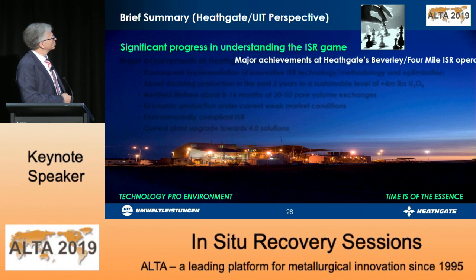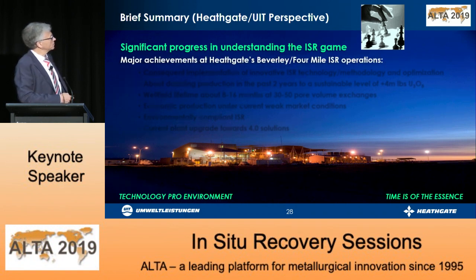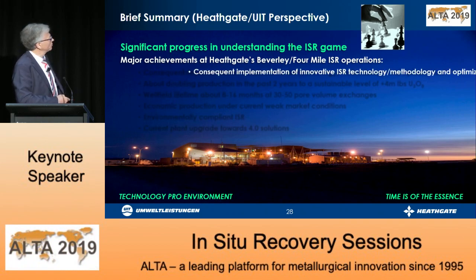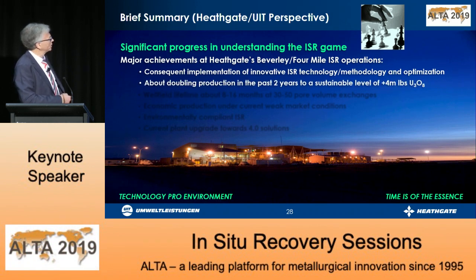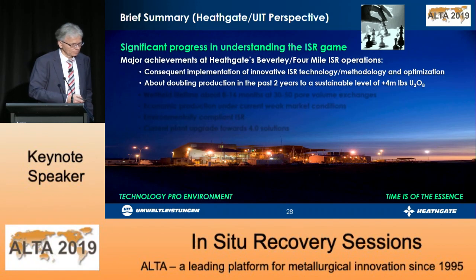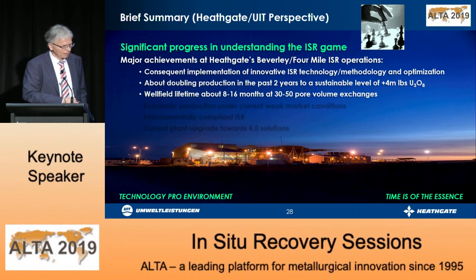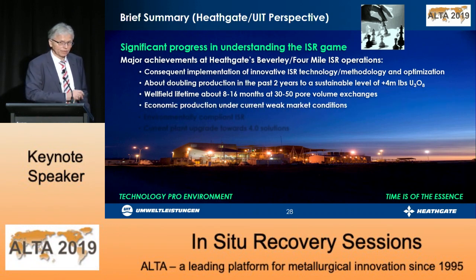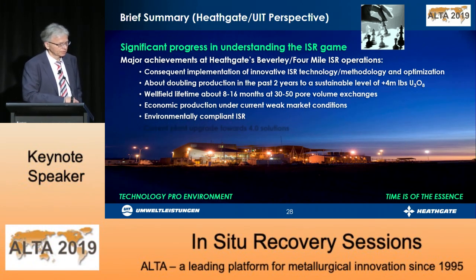So significant progress has been achieved in understanding the ISR game, and the major achievements by Heathgate at the Beverley Four Mile operations, consequent implementation of innovative technology, about doubling the production in the past 2 years to a sustainable level of plus 4 million pounds per year. Wellfield lifetime about 8 to 16 months, very short, combined with 30 to 50 pore volume exchanges. And economic production has been realized under current weak market conditions. Our operations are environmentally compliant, and the current plant upgrade opens us the way towards 4.0 solutions.